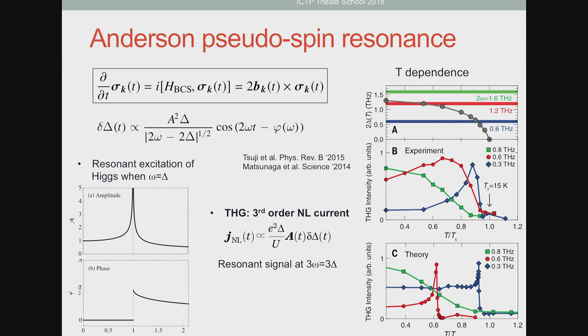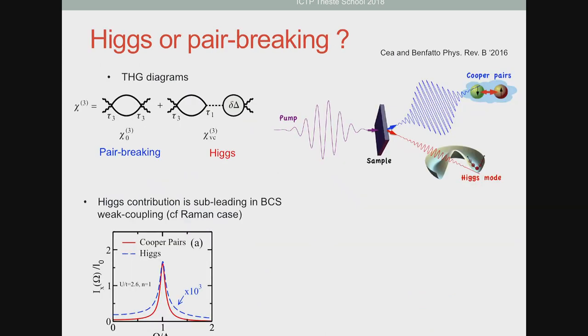And actually, these people, Tsuji and Aoki, when they computed the third harmonic generation response, worked in an approximation where the pair breaking peak was zero. And this is because they took essentially constant vertices, so it's screened out. But of course, we know from the Raman scattering point of view that this is a special case. And in fact, if you don't take this special case and you take a very general calculation that was done by Cea and Benfatto, you realize that once you compute the third order nonlinear susceptibility, so the third harmonic generation, this is essentially the same diagram as in Raman, except that the incoming frequencies are slightly different. But it's essentially the same diagram as with Raman.